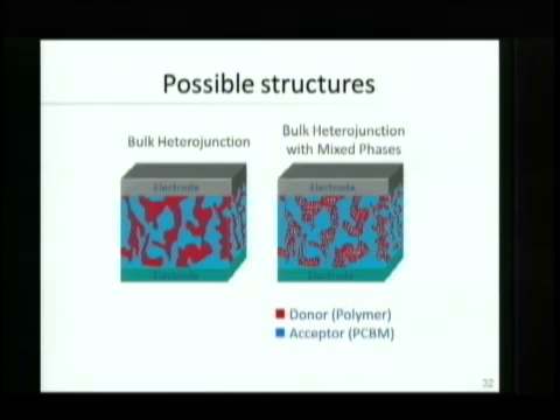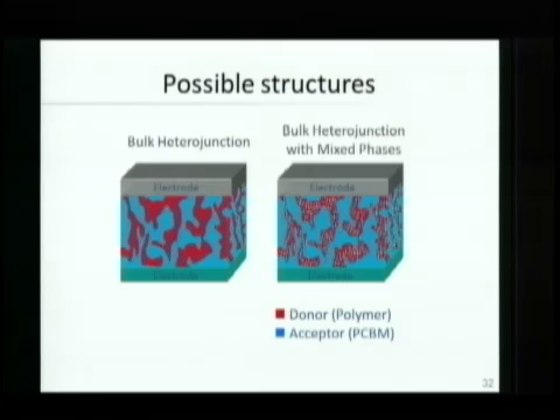So this brings me to the research that we do right here at SLAC. To make these solar cells work well, we need to know where the donor molecules are and where the acceptor molecules are. We have to make sure that the regions of the donor are small. They can't be more than about 10 nanometers. If they're wider than that, the excitons might not make it to the interface. But we also have to make sure that the electrons have a pathway to get to the top electrode and that the holes have a pathway to get to the bottom. If there are isolated islands, then the charge carriers can't get to the electrodes.